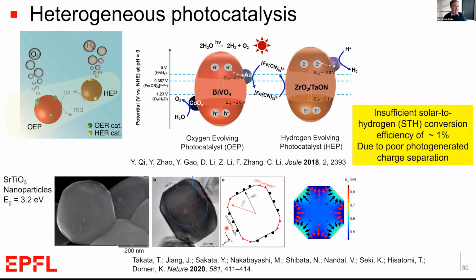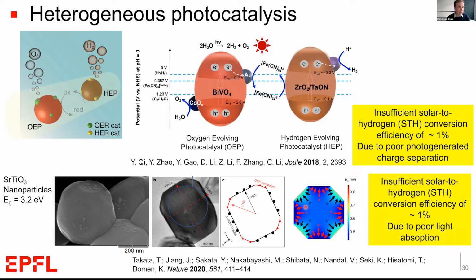I want to note that there is a clever way that we can get charge separation in inorganic materials, and that was recently highlighted again by Professor Domen in Japan, where he showed these single crystal strontium titanate materials. Because of their different crystal facets, which interact slightly differently with the water, adsorbing slightly different species and generating a small difference of potential between the different facets, that potential difference can actually create an electric field that can drive charge carrier separation in these nanoparticles or microparticles. However, a material like strontium titanate has a large band gap and doesn't absorb a lot of light. So work still needs to be done to figure out what other systems this could be applied to.